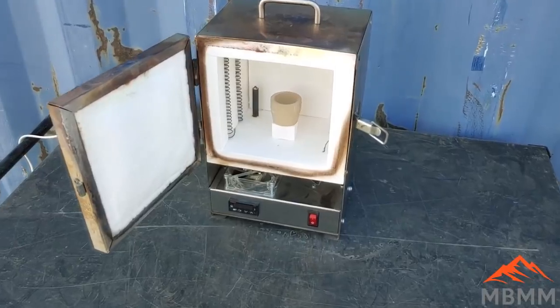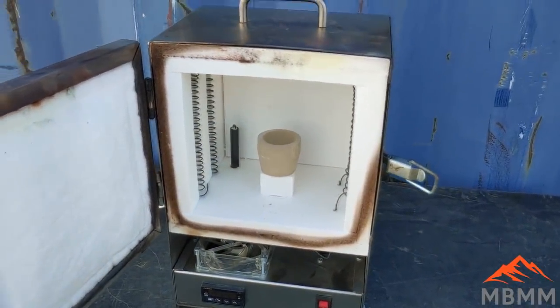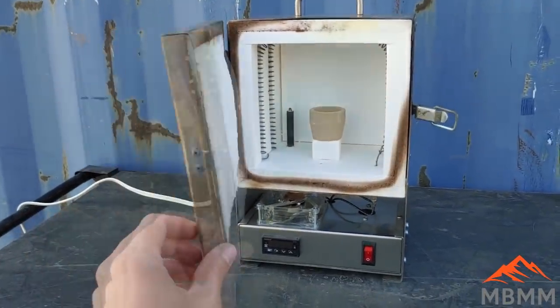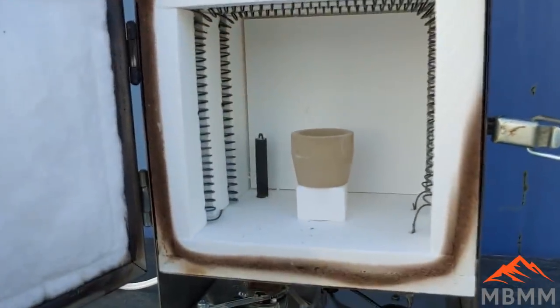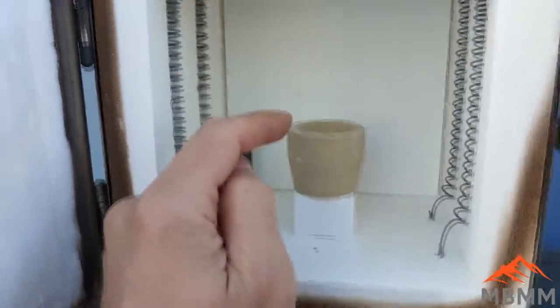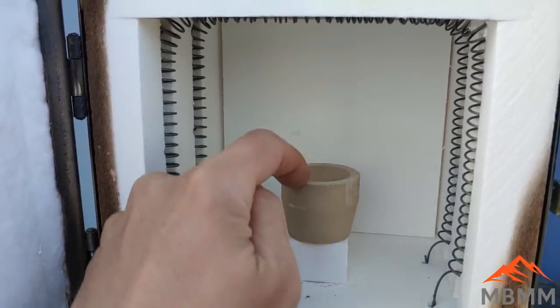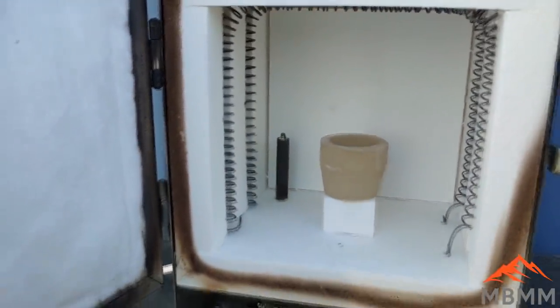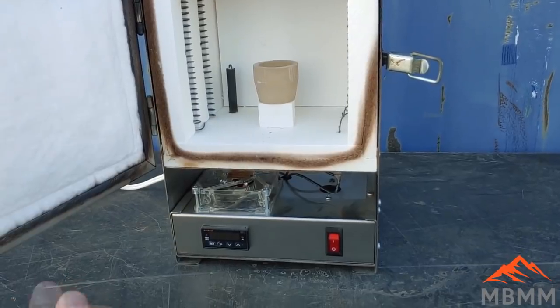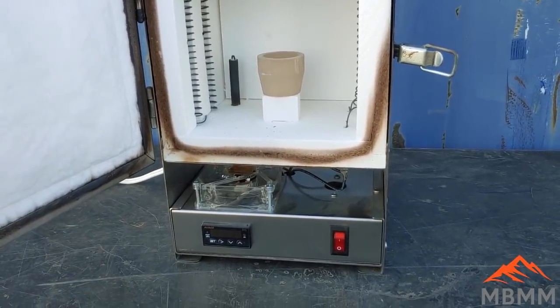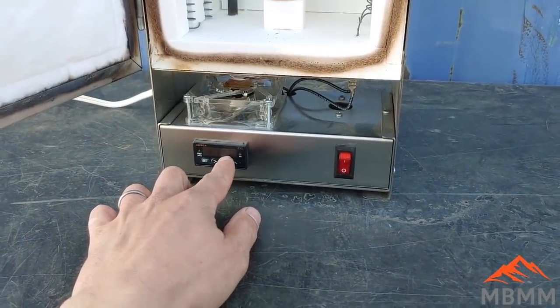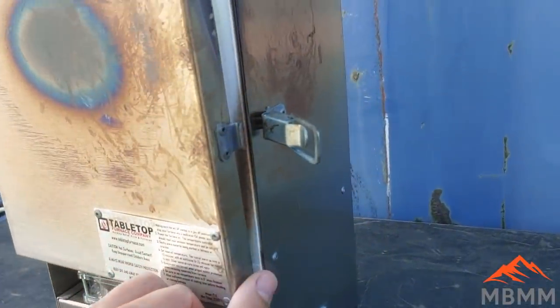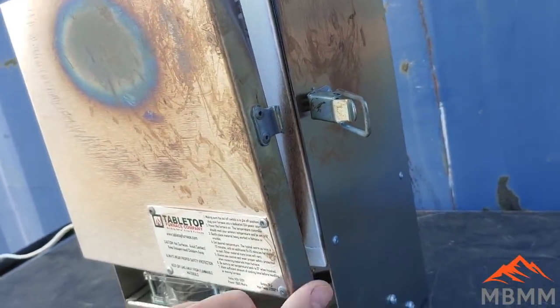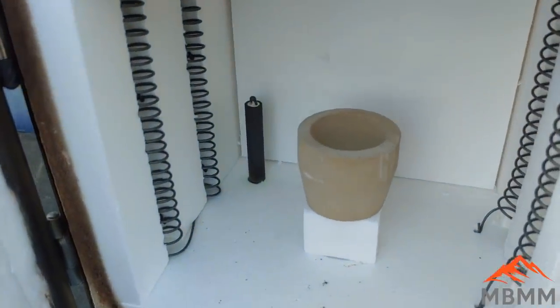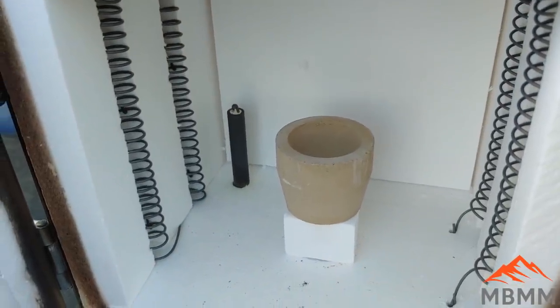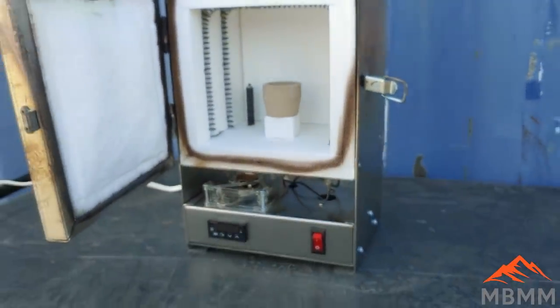I wanted to take a second here and show you guys, I've kind of improved my cupelling method. This is a little electric furnace, and it's got the coils in there. This is where I'm starting to do my cupel. When I get the lead button, I put it in this cupel, which absorbs the lead oxide as we heat it up. In the past, I've done this in my gas furnace, but it's really hard to control the temperature and get a nice even heat. Whereas with this one, when I turn it on, I can control the temperature right down to the degree. For the oxygen, I can just crack the door a little bit and let the air blow through. It oxidizes the lead. I can control the temperature really nicely, and we get a really nice precious metal bead in the bottom of that cupel when it's all said and done. So I'll show you the process, but wanted to walk you through my new improved method here.